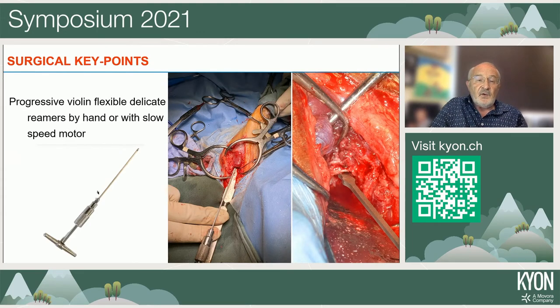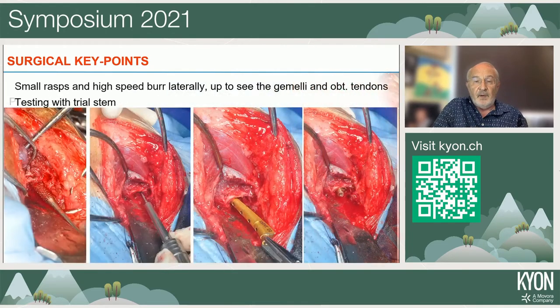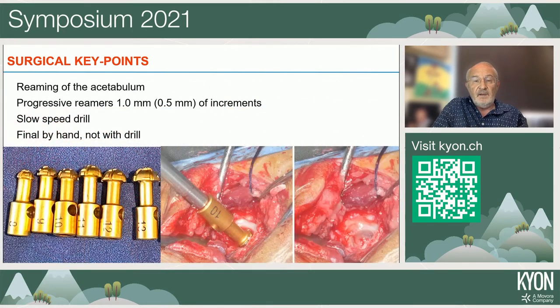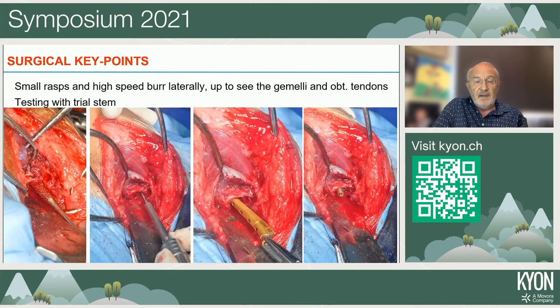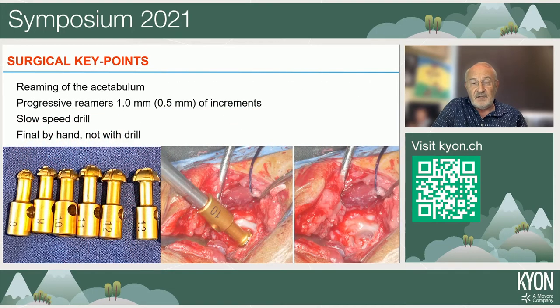Very interesting are those new nitinol flexible reamers, with a violin shape at the tip, and so we can use that by hand or with a slow speed drill, so we can prepare very well the femoral canal. Of course, we need also to go with small rasps, rasps again with the high speed burr. And then we test with the trial stem, as is done regularly for large animal, for larger dogs.